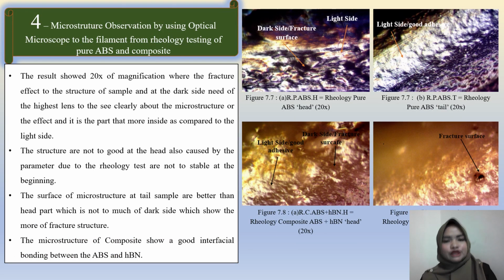Then for number 4, microstructure observation using an optical microscope of the filament from rheology testing of pure ABS and composite. The results show 20 times magnification, where the fracture affects the structure of the sample at the dark side, the highest lens, to see clearly the microstructure or the defect, and it is the part that is more inside compared to the light side.